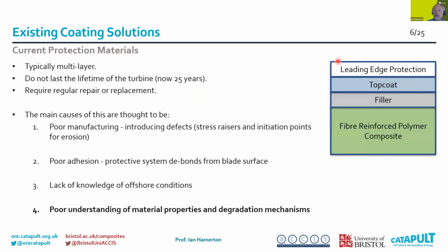Here's a schematic showing a section through the turbine blade. So we have the structural fiber reinforced polymer composite at the base, which will be glass fiber reinforced polymer in the context of smaller turbine blades, and increasingly for the longer structures, carbon fiber reinforced materials, covered with a filler and then a top coat, and then the leading edge protection. So it's a multi-layer structure. Each of those materials are really quite dissimilar. They have very different mechanical, elastic properties. They have quite different acoustic properties.